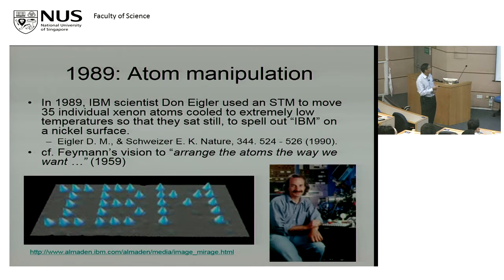And this very famous image by IBM was the first time Don Eigler in 1989 in IBM Almaden used an STM tip, or his student or postdoc, to move individual atoms on a metal surface to make the words IBM. Of course, it took many hours to do this because it takes a while to pick and push the atoms around. And it was done at 4 Kelvin, at low temperature, so that these atoms don't run away. Very nice for publicity purposes. We haven't yet found a use for this, right?